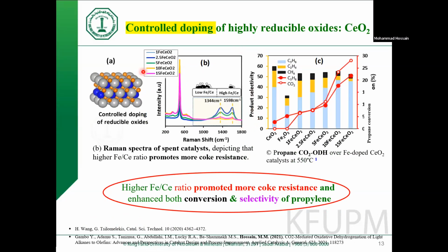Here, the control of the active site has been investigated by masking or by controlling a second metal. So first, ceria was used, which is a good candidate as a redox metal. So it can offer reducible oxygen easily. However, when too much oxygen is provided to the hydrocarbon, the possibility of complete oxidation is there. So here, introduction of iron helps to control that, and it also creates a situation to prevent coke formation. Consequently, the selectivity of the product has been significantly increased in the case of the iron-modified ceria catalyst.